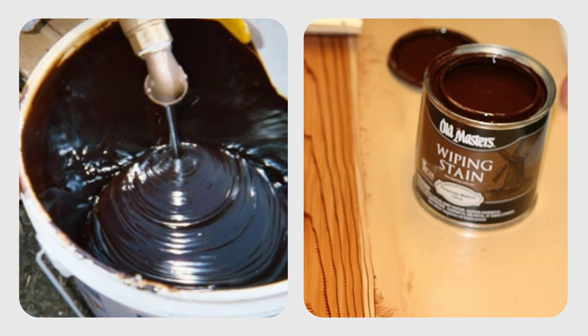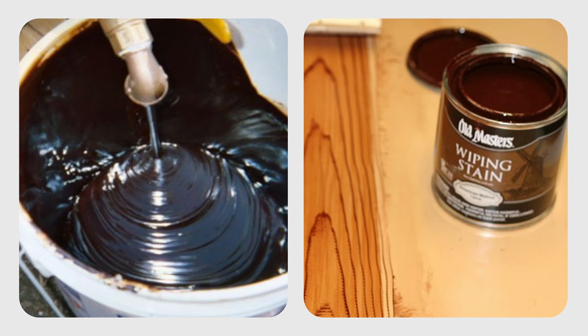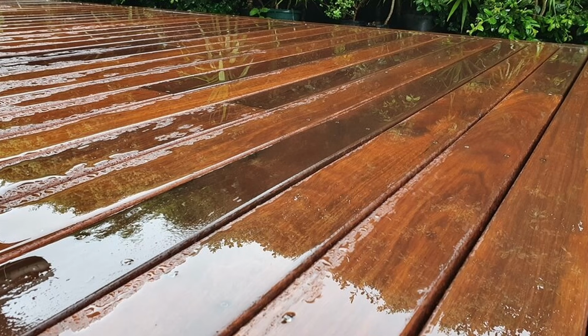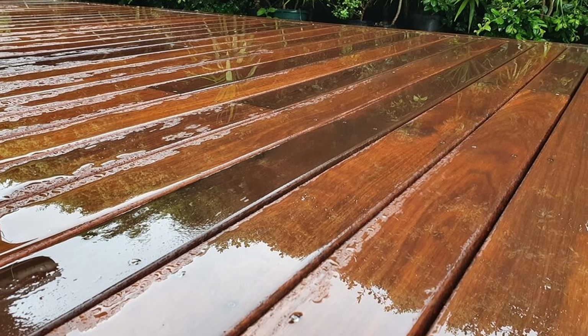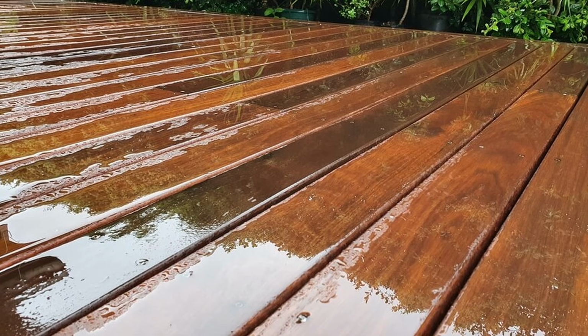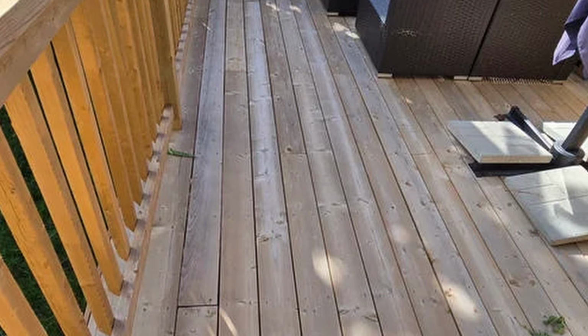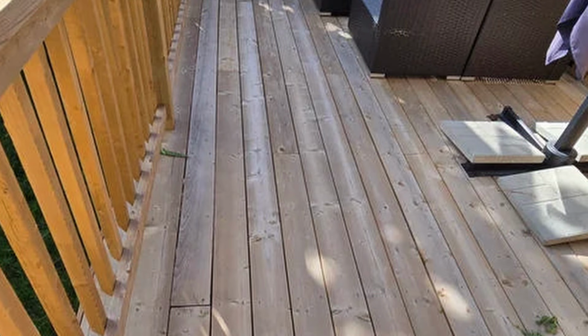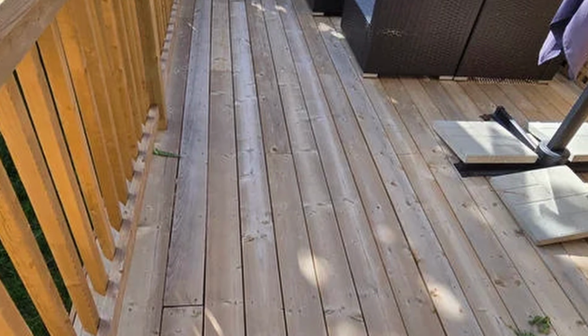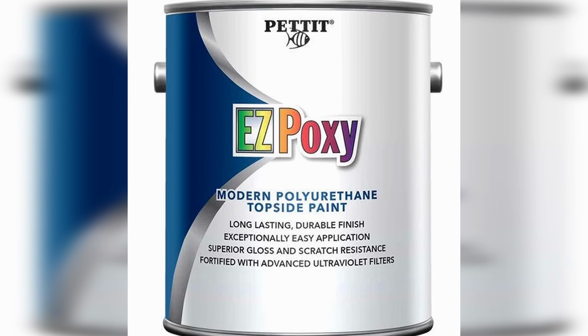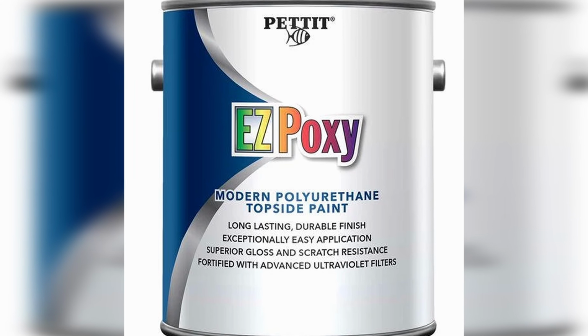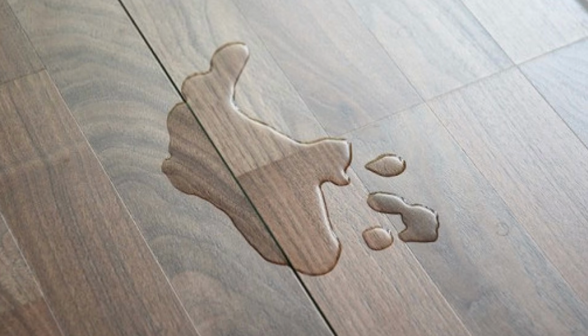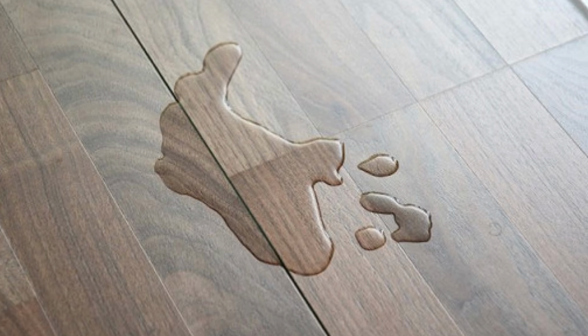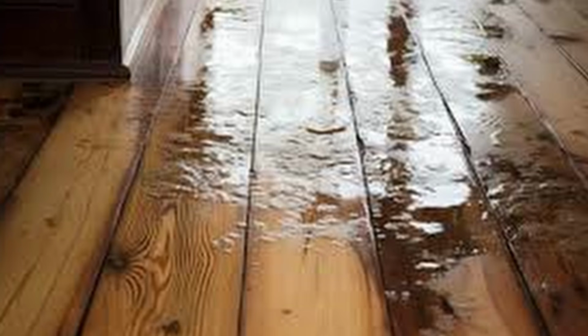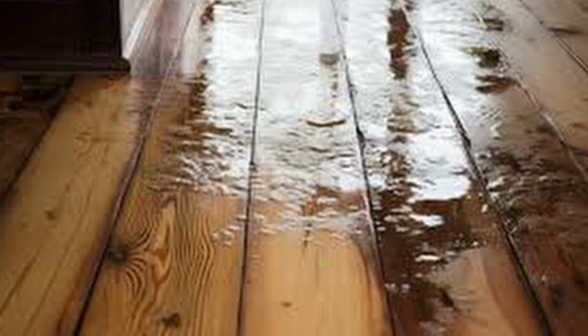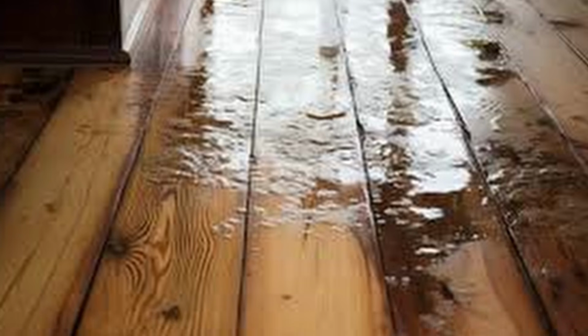Here's the critical difference between pine tar and modern paint. If water does get into the wood, through a crack or a fastener hole, the tar allows that moisture to evaporate back out. When the sun heats the wood, water vapor is pulled through the tar layer and released. Modern polyurethane paint, by contrast, traps moisture inside. If water gets under the paint film, it can't escape. This creates a greenhouse effect that accelerates rot. The paint that was supposed to protect the wood ends up killing it.